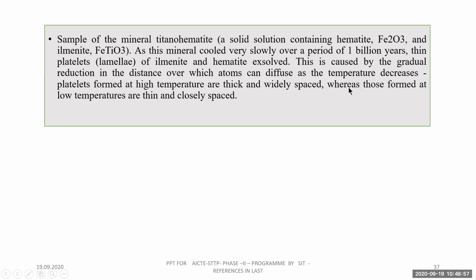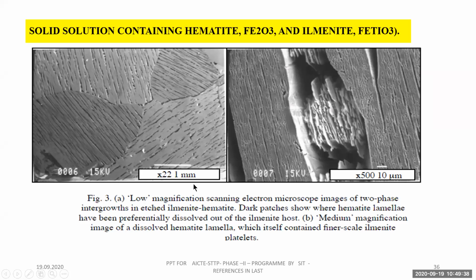It's a prolonged cooling, with the formation of ilmenite and hematite, and there is a thickening of the platelets. Platelets formed at high temperature are thick and widely spaced, whereas those formed at a low temperature are thin. And see, where the temperature is high, that area is thick, and where the temperature is lower, that area is thin. Thick areas are widely spaced, thin areas closely spaced. So this is the formation, but how do the imaging techniques and the instrument work at low magnification?